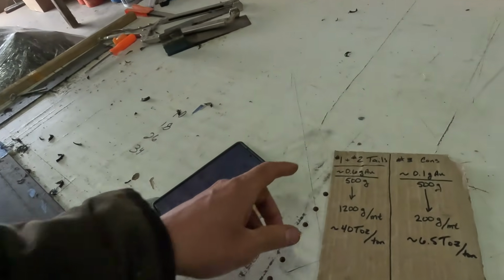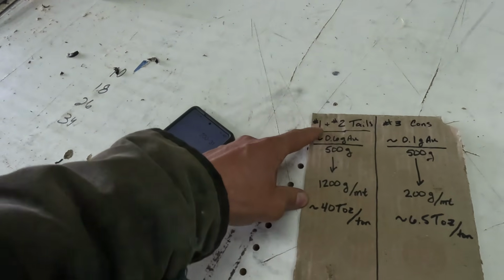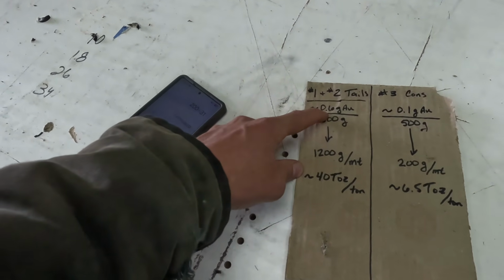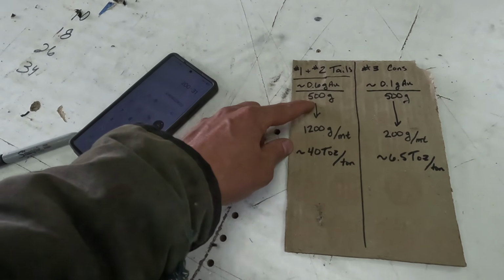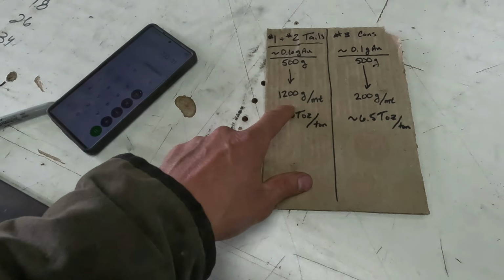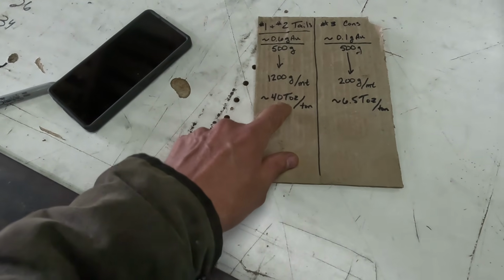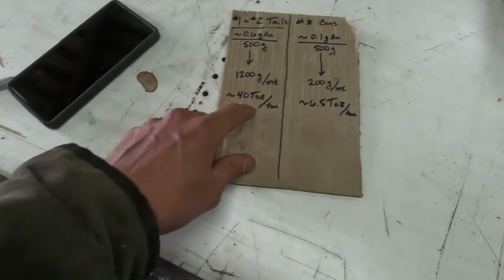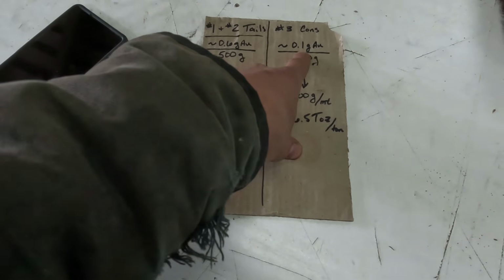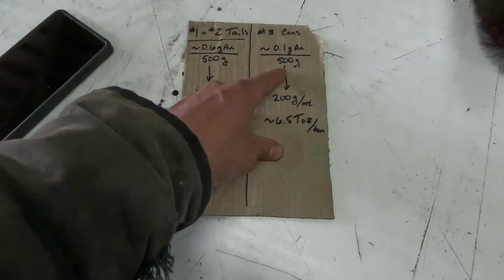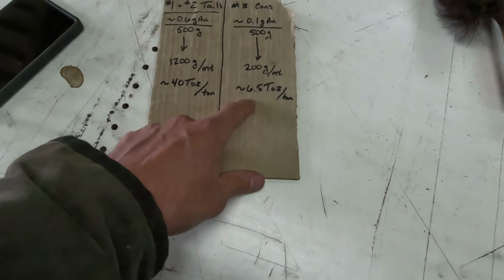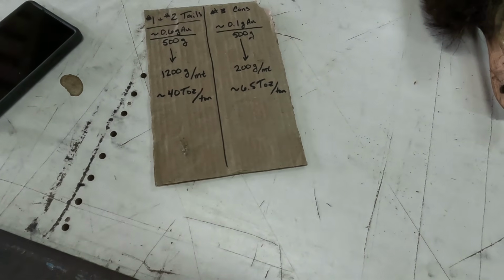All right, I wanted to do a little math here to show you where we're at. This is the number 1 and number 2 panning tailings. Had about 0.6 grams of gold in 500 grams of material. That ends up being 1,200 grams per metric ton, or about 40 troy ounces. The number 3 cons had about 0.1 grams of gold in 500 grams of material, 200 grams per ton, or about 6.5 ounces per ton.